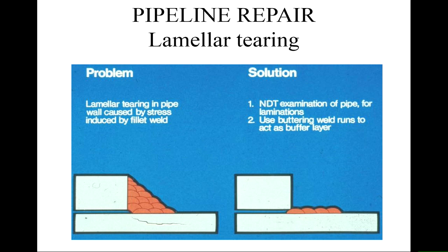So if the buttering runs are done correctly, you'll refine the microstructure in the region around those welds, and then the lamellar tearing isn't such a problem, because if you think about the welding process, the linear arrangement of microstructure is removed in the heat affected zone. So we have a more equiaxed, as we call it, a more 3D microstructure under those circumstances. So the buttering runs act as a buffer layer, and then you can weld onto them with a normal process. And these buttering runs might even be allowed to be done and cooled to room temperature before you then do the rest of the